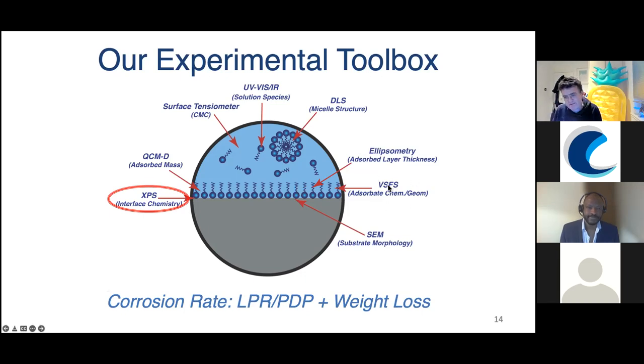So, for instance, we're developing vibrational sum frequency spectroscopy. And that's a nonlinear optical technique. It involves lasers, and it gives you vibrational information that is essentially interface specific. And you can look at adsorbate chemistry and geometry. So, for instance, we look at the ordering of the CH3 groups on the tail groups of the molecules and see whether it's well ordered, laying flat, standing upright. And this you can truly do in situ. And we have measurements on that. I just didn't talk about that today.